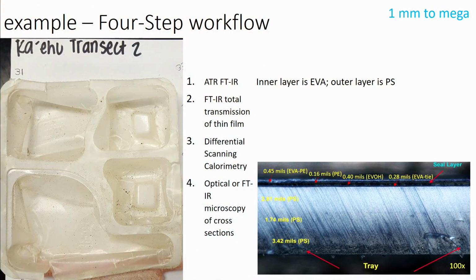This is a snack food tray that was found as marine debris on a Hawaiian beach. When we put it on the ATR FTIR, we scanned the inside of the piece, and it turned out to be ethylene vinyl acetate. If we flip it over and on the bottom of the tray, we analyze it by ATR, we see polystyrene. If we work our way through this process, what we end up with is the cross-section picture under microscope and all the different layers in there.